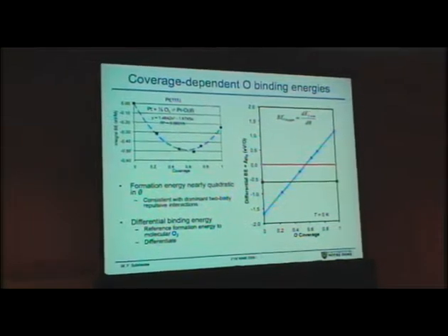All right, so now if you're going to do NO oxidation catalysis, you've got to be able to exothermically adsorb O2 on the surface. That means you have to have a binding energy that's below that line. If you're going to do NO oxidation, you also have to be able to exothermically remove an oxygen from the surface. We know what the ONO bond energy is, and I told you that that's a small number, it's about 0.6 volts, that means that I have to bind oxygen weaker than what's shown by this green line here. So if I'm going to do NO oxidation on this surface, I have to do it in this bond energy region.